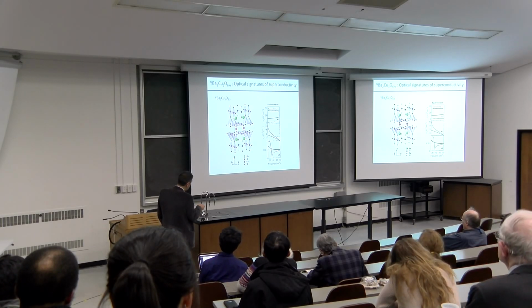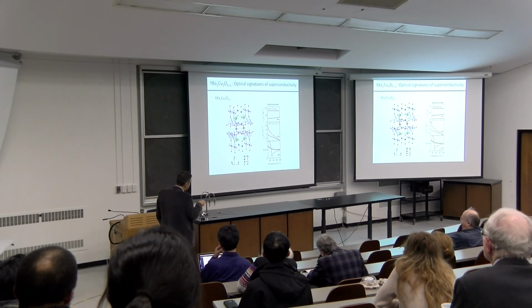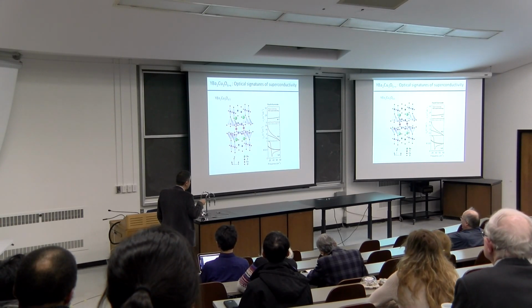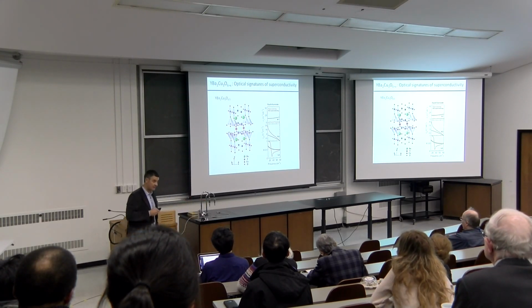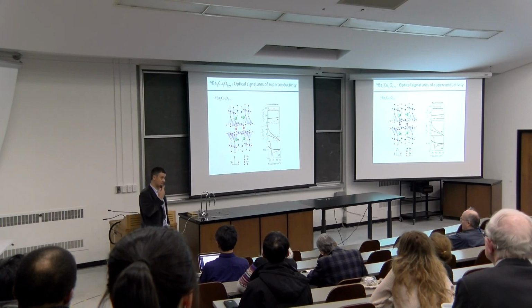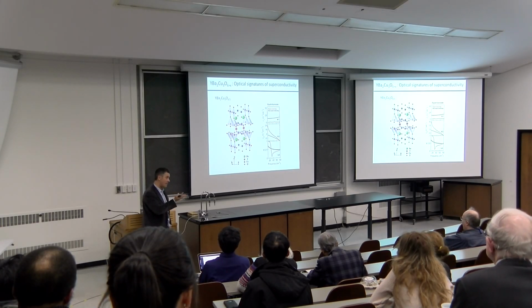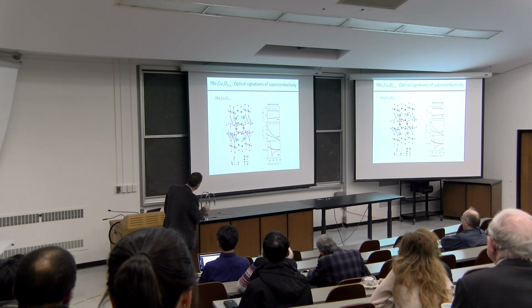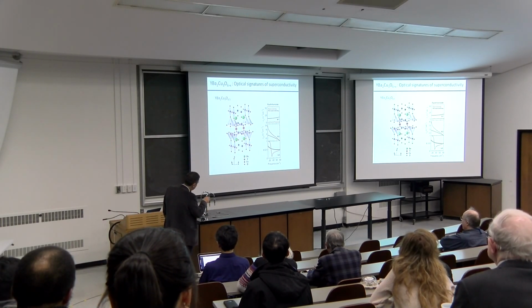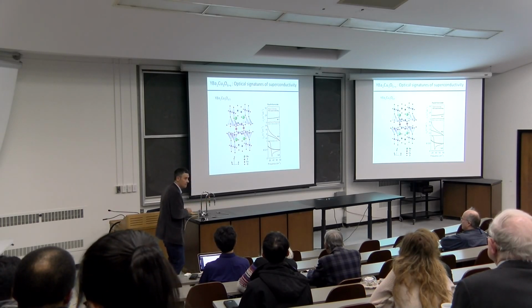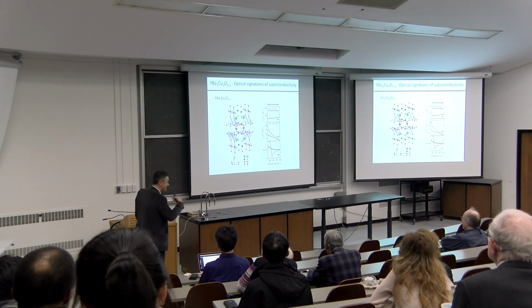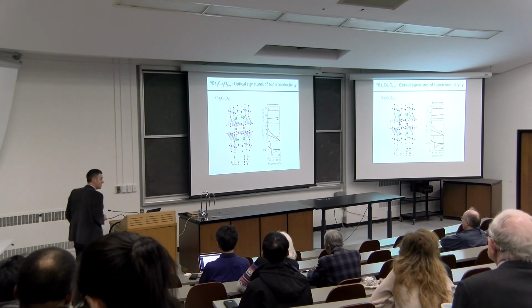Another feature that I'm looking for is the response in the imaginary part of the optical conductivity. So the proportionality constant between the current and an applied electric field tends to diverge toward zero frequency. And in the real part of the optical conductivity, one has basically 0 down to 0 frequency, where one has a delta function. So these features are uniquely identified as features of a superconductor.